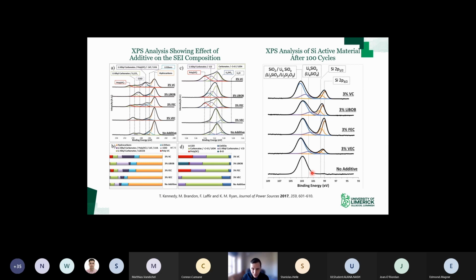So it's consuming the active material. It's not only that the solvent molecules are decomposing, they're consuming silicon at the same time. And they form these lithium silicates, so these LixSiOy type compounds. Once they form, that's irreversible, so you won't get the elemental silicon back. So this really explains why the no additive material doesn't form that ligament type structure, doesn't form that stable morphology, because basically the silicon is being consumed continuously. So you get that consistent capacity degradation when you don't use an additive.